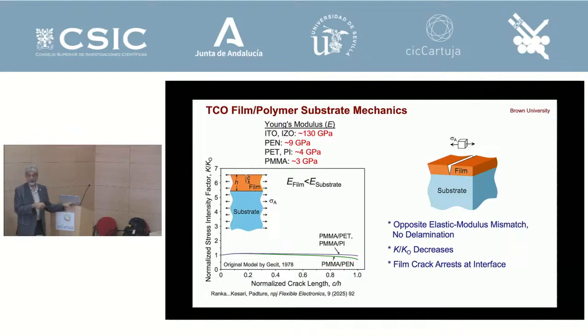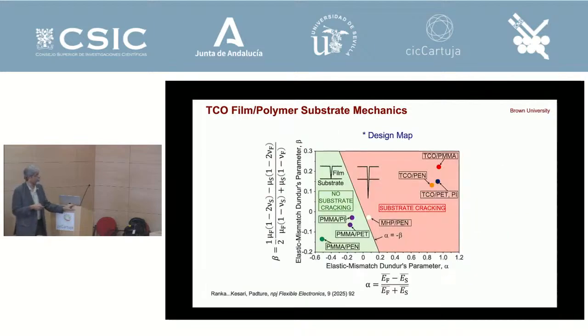If we have a compliant film, low modulus film on a substrate, then actually it arrests. It goes the other way, right? The film would not fracture, sorry, the substrate will not crack, right? So based on that, we created this design map.